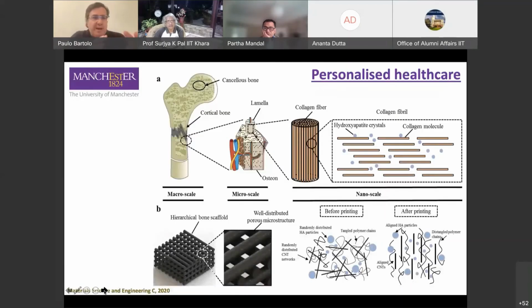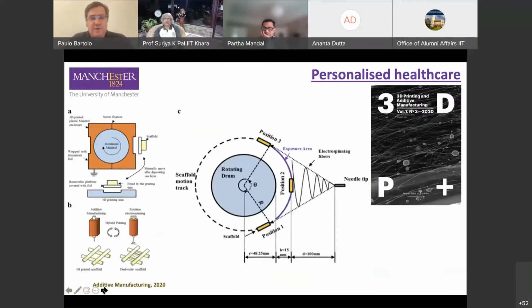We were able also to create biomimetic constructs using extrusion-based machines and a combination of biocompatible and biodegradable polymer with nanohydroxyapatite and multi-wall carbon nanotubes. After printing, we observed that, first of all, the multi-wall carbon nanotubes were highly aligned according to the printing direction, similar to the collagen molecules in bone, in between a polymeric matrix containing nanohydroxyapatite particles, similar to the hydroxyapatite crystals in bone. So we are able also to reproduce the structure and the composition of bone.